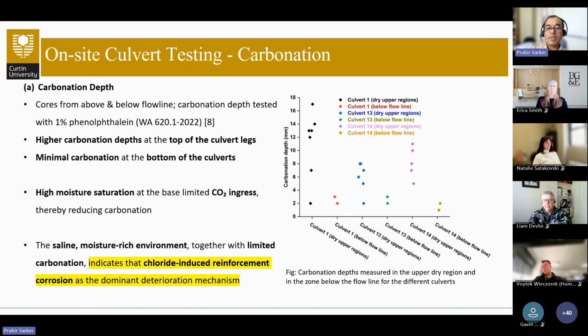For the three culverts presented here, in some culverts the carbonation was up to 15-16 millimeter depth, in others it was up to 8 millimeter, but at the bottom of the culvert it was very low.